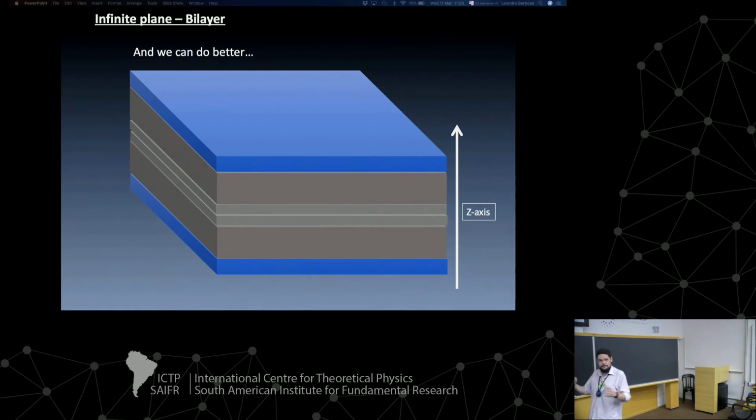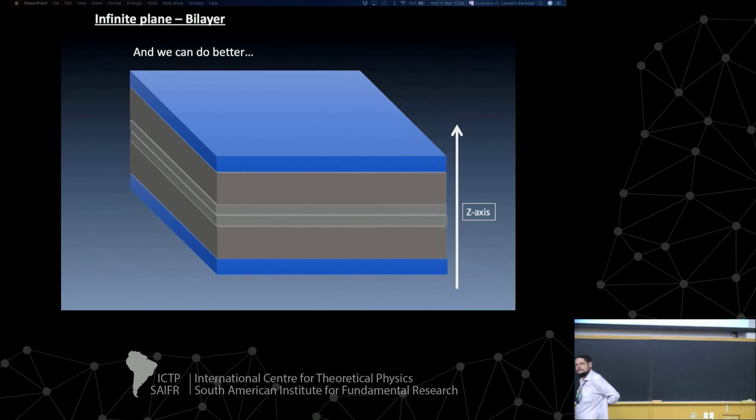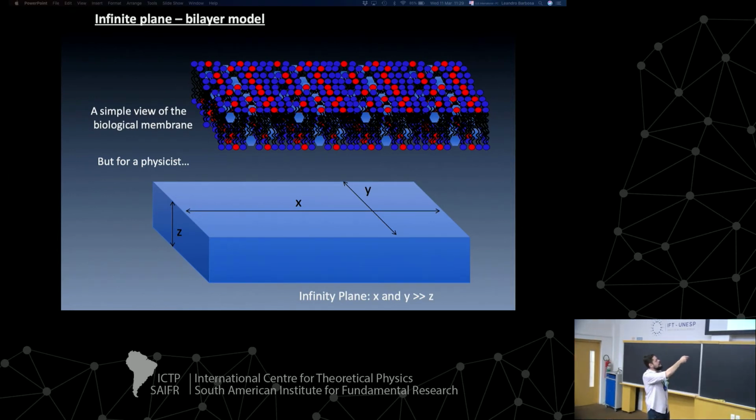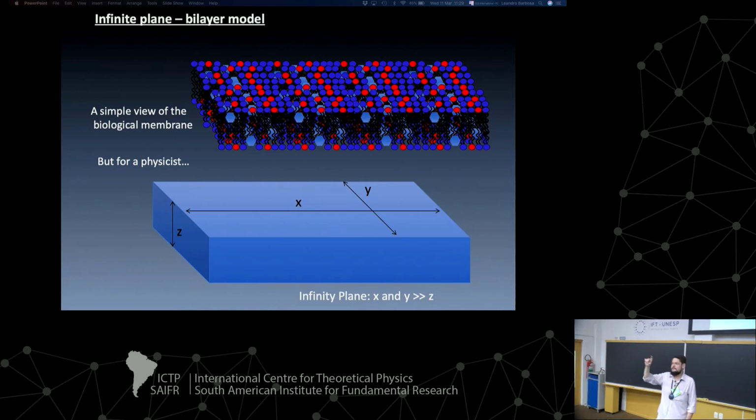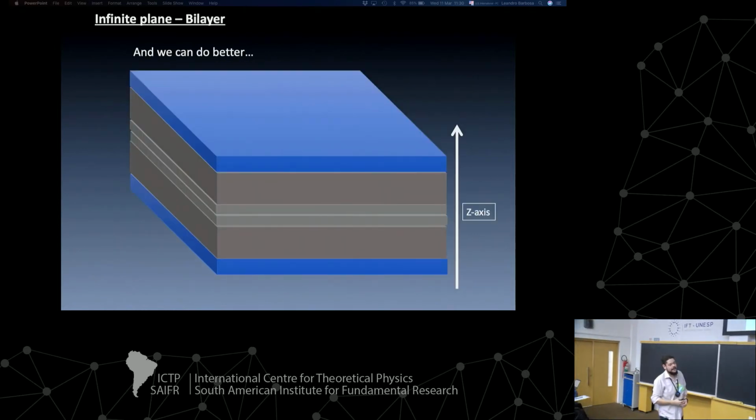Let's see if we can make some calculations and find the Z direction. We like to make models for this stuff, like the spherical model we talked about yesterday. Now we have the plane, but I will try to improve this physical model a little bit by supposing that I know that the inner part of my bilayer is hydrophobic. In the middle of the bilayer itself I have a CH3 region. The tail is mainly CH2, methylene groups region, which has a slightly larger electron density as compared to the CH3. And the polar head group has a higher electron density.